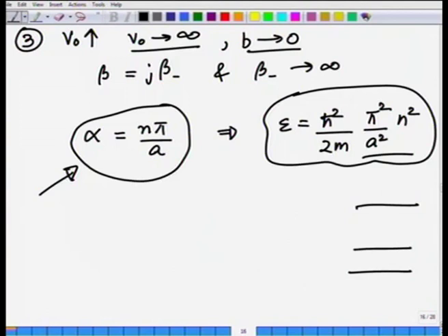Really striking results: if you use periodic potential, of course, it recovers back when V 0 is 0, we recover back near free electron theory. When V 0 is infinity, then we start looking at a particle in a box like solution, that means discrete energy levels. And in between, for all intermediate values of potential, as a consequence of periodic potential near k equal to 0, that means reciprocal lattice points and Brillouin zone, we start seeing a discontinuity, disallowed values of energy.